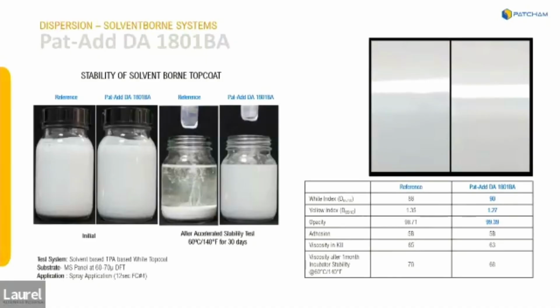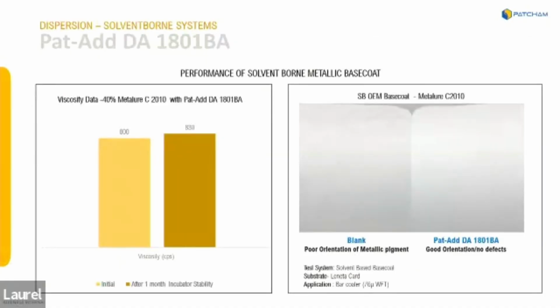So look at those two panels on the right. And these were done with effect pigments, metallic flake pigments, to provide the lightness. And you can see with and without this particular leveling additive, its impact on the orientation of some of these coatings now that are being developed that are challenging for metallic flake orientation. So just another approach of an additive that provides multi-benefits to your application process.